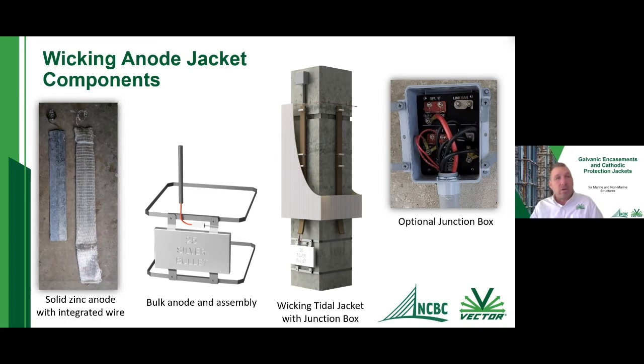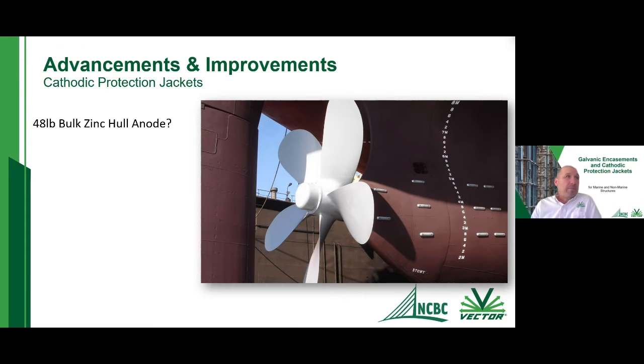Or even external structural cages, if you're adding another cage of reinforcement to make it a structural jacket as well. As I mentioned, another advancement with the Tidal Plus was moving from a 48-pound bulk zinc hull anode. Traditionally, a bulk hull anode had been used. These are anodes that have obviously been used on boat hulls before. They were used because it was a zinc anode, and they needed compatibility with the zinc mesh that was inside of the jacket.